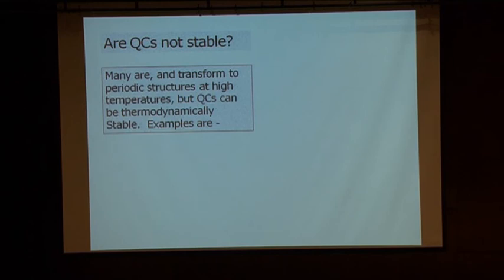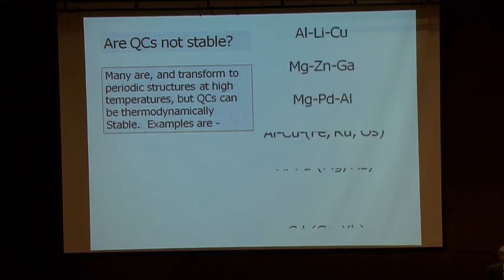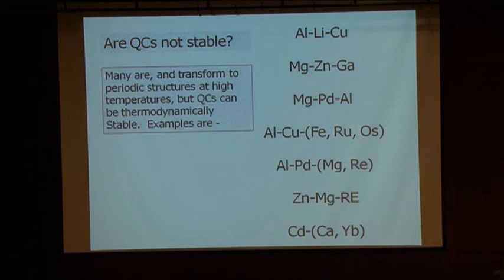Maybe they're not stable. Well, many are not stable, but some are stable. And the ones that are not stable, you have to heat up to 300 or 400 degrees C in order to transform them. Below that, they're stable. So for any practical purpose, they are stable materials. That's not the answer.